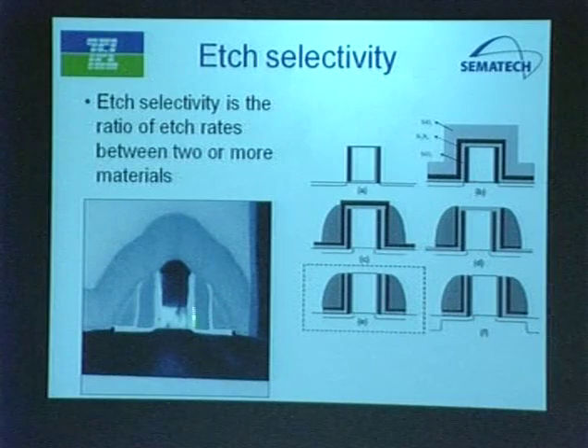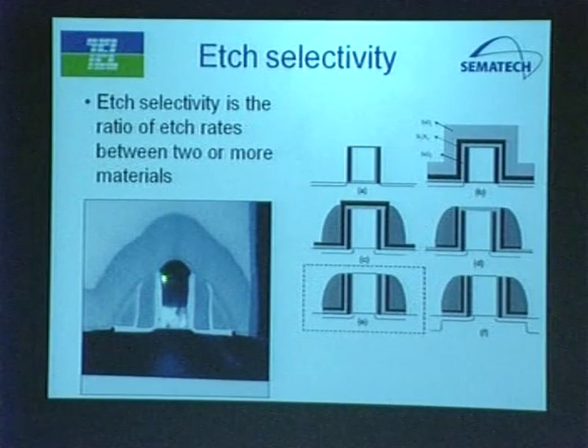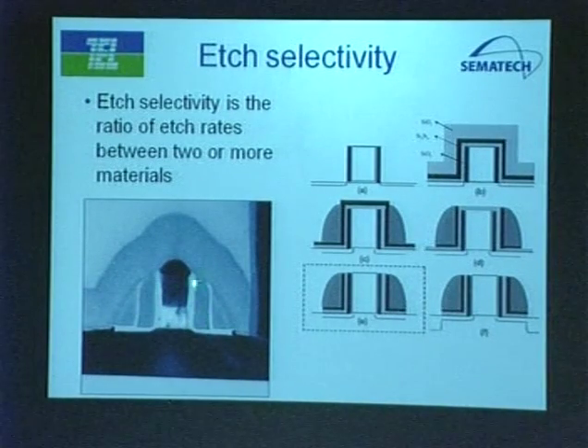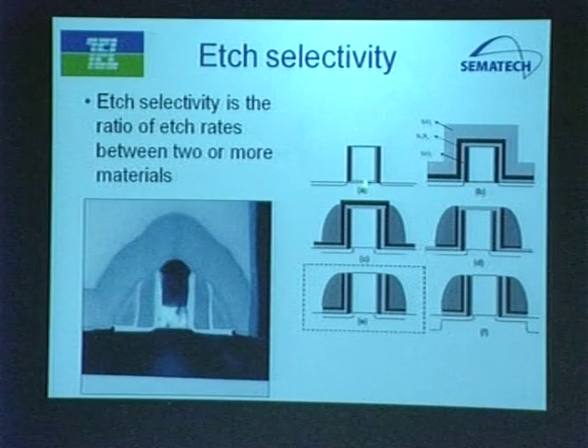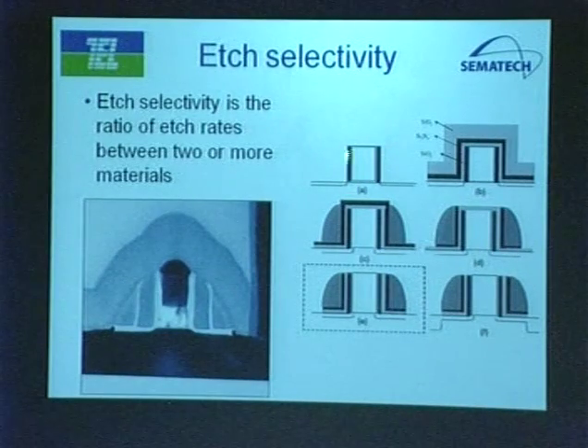You look at this and you say, well, there's all kinds of things going on here. Just to give you an idea, this is a gate material. We're looking at a transmission electron microscope image here. This is a TEM. You're looking at a SiO2 film, a silicon nitride film, an SiO2 film, a silicon nitride film. How are those created? Well, this is the gate, and these dark lines represent the first material that's deposited here, probably by a plasma system. And actually, it's uniformly deposited on this surface, down and over.